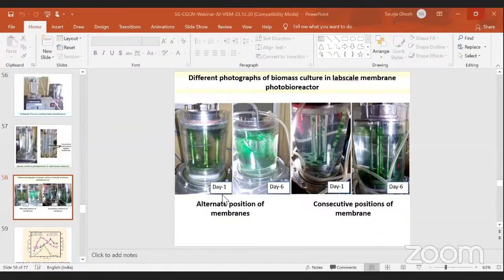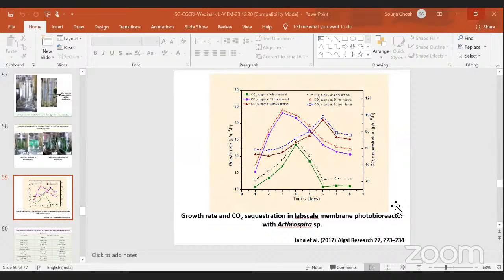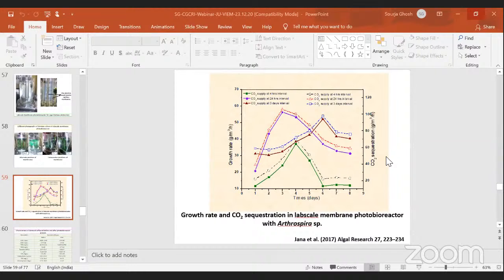And these membrane modules are arranged in various configurations to see their effect on the mass transfer. So this is the alternate position, and this is the consecutive position of membranes. So when we summarize the result of the experiment, growth rate and CO2 sequestration in lab scale membrane photobioreactor with Arthrospira species, we found that a 24-hour interval of CO2 providing is optimum for higher biomass growth, and this resulted in considerable CO2 sequestration also.